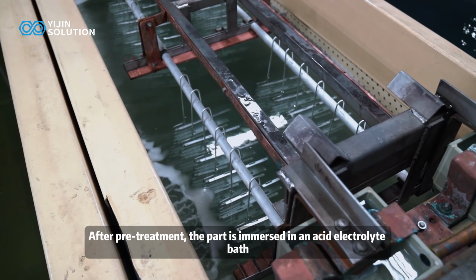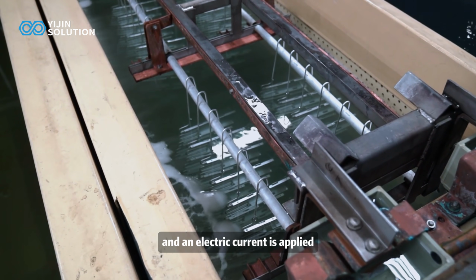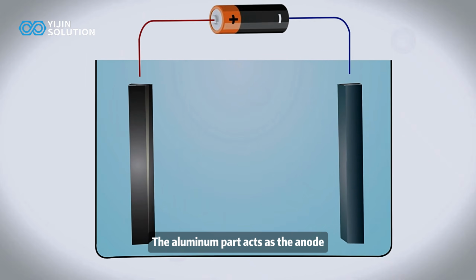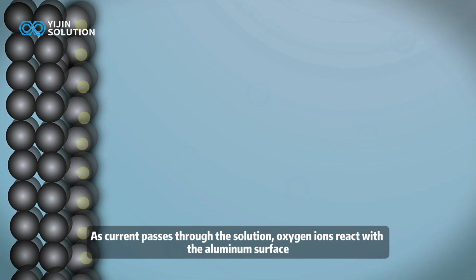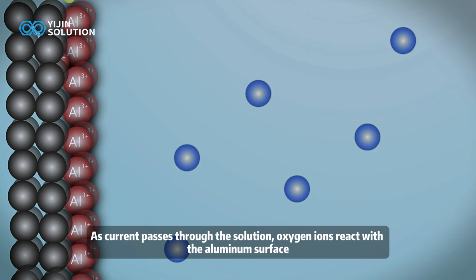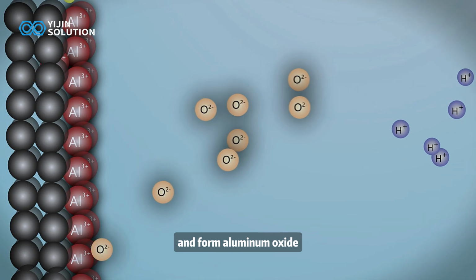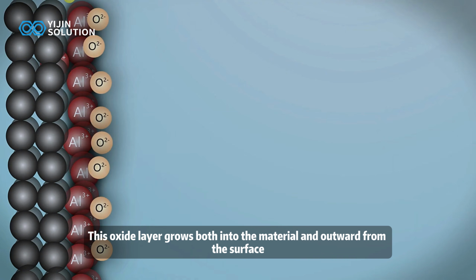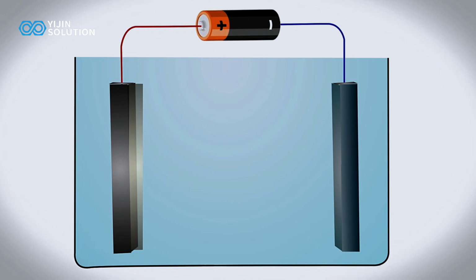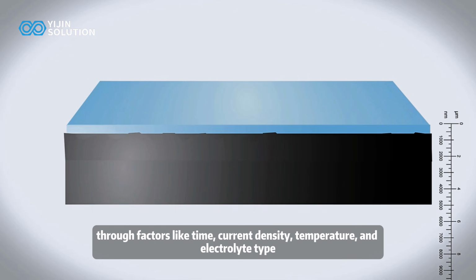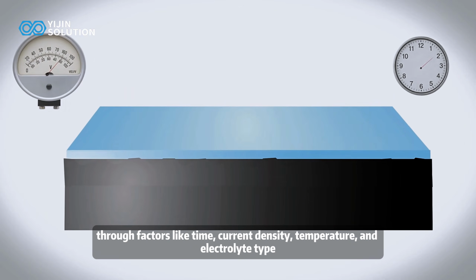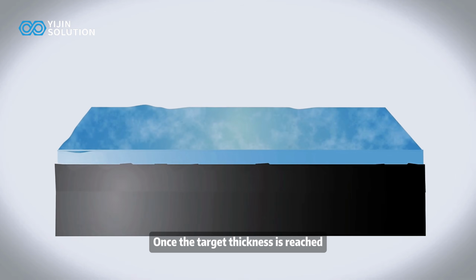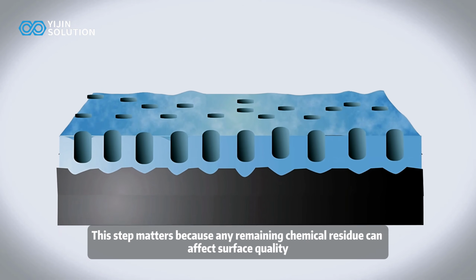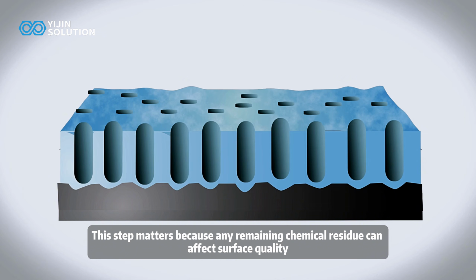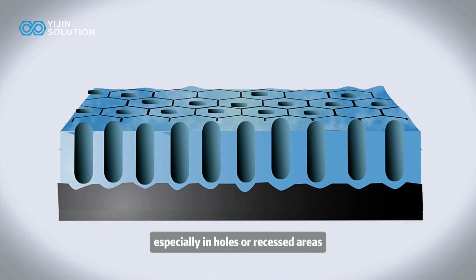After pretreatment, the part is immersed in an acid electrolyte bath and an electric current is applied. The aluminum part acts as the anode. As current passes through the solution, oxygen ions react with the aluminum surface and form aluminum oxide. This oxide layer grows both into the material and outward from the surface, which is one reason anodizing is not simply an added coating. Its thickness is also carefully controlled through factors like time, current density, temperature, and electrolyte type. Once the target thickness is reached, the part is rinsed. This step matters because any remaining chemical residue can affect surface quality, especially in holes or recessed areas.